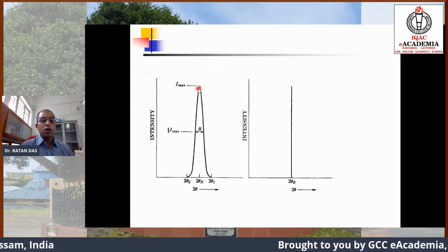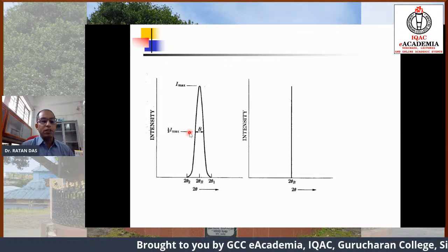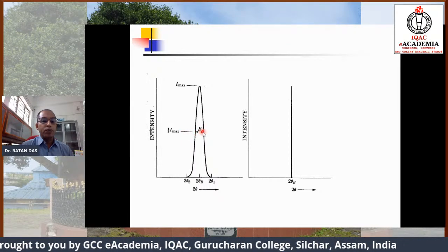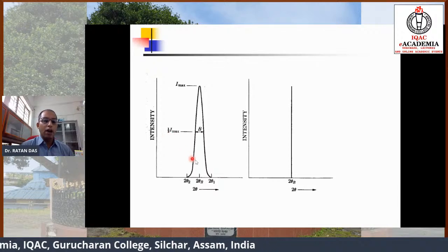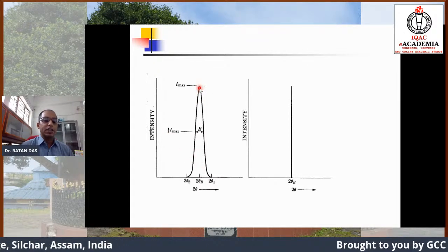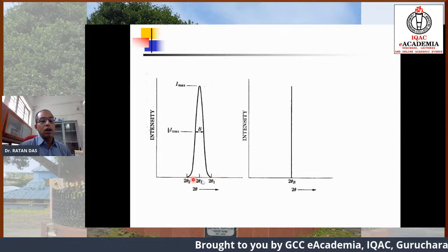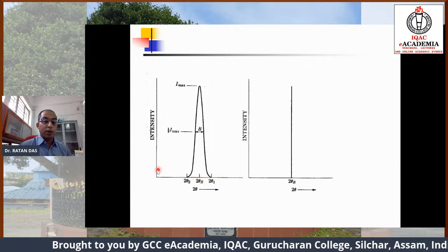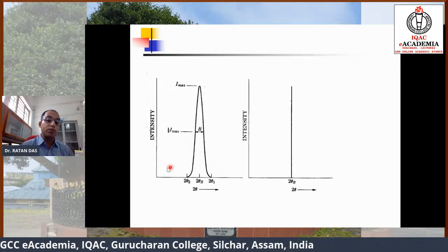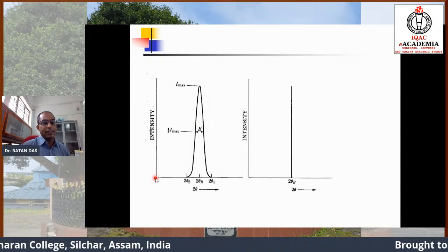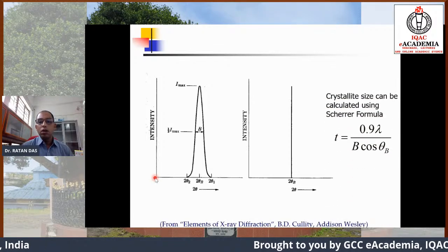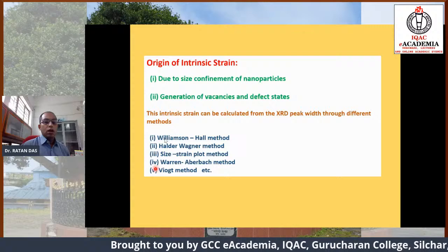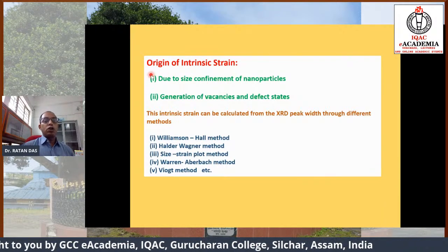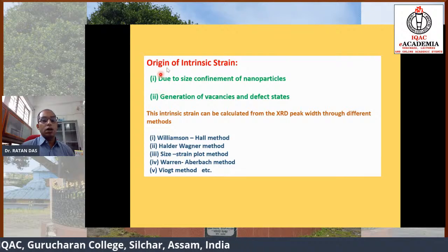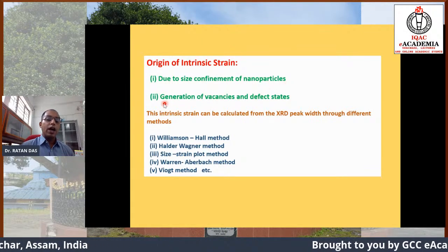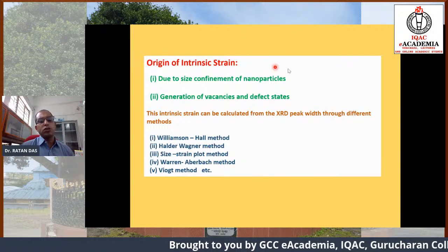This is the maximum intensity. This is the half maximum intensity, and this is the width, I mean the full width at half maxima. Half maxima means half of the intensity of the X-ray diffraction pattern, and here lies the base. We measure the intensity from the base of the X-ray diffraction pattern, not from the axis. Again, I want to tell you that the origin of this intrinsic strain is nothing but the size confinement of the nanoparticles and the generation of vacancies, defect states, or rearrangement of all these things.